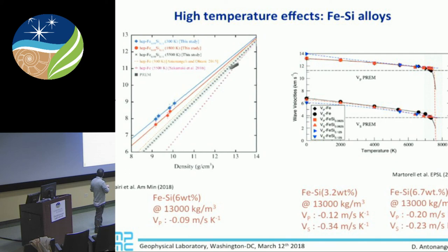So it's something that goes beyond the quasi-harmonic potential. It's beyond parabolic interatomic interaction, which is something that enters explicitly into the calculation and that has been observed in the experiment as well. If this system were truly harmonic, you should not be able to resolve this. The fact that this is coming from anharmonicity is also quite evident from the fact that at lower density, where thermal expansion is larger, the effect for the same temperature is larger, and the effect becomes smaller with increasing compression, where the thermal expansion is less.